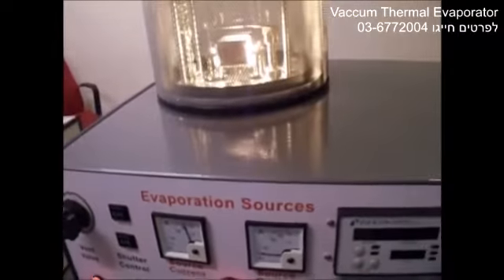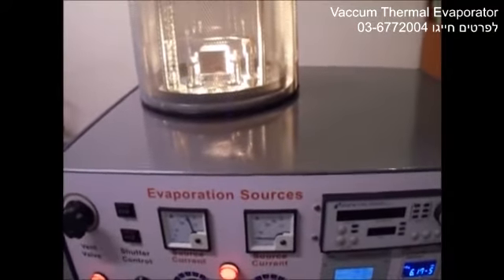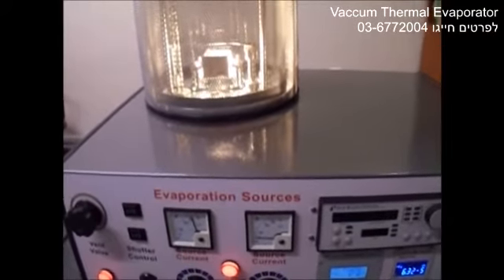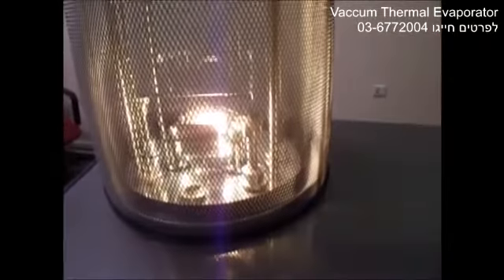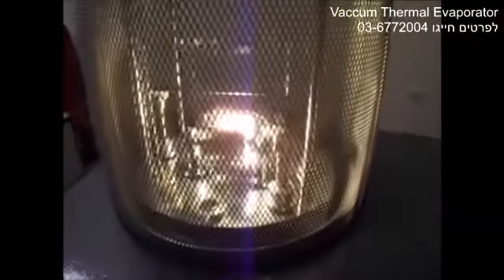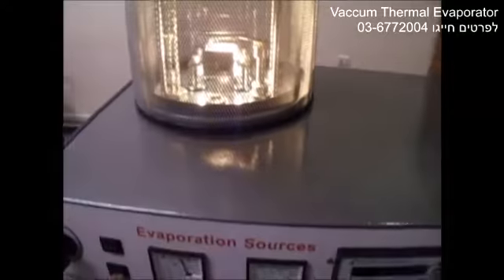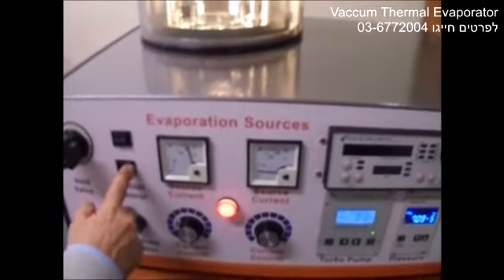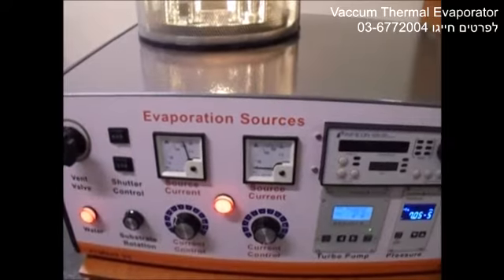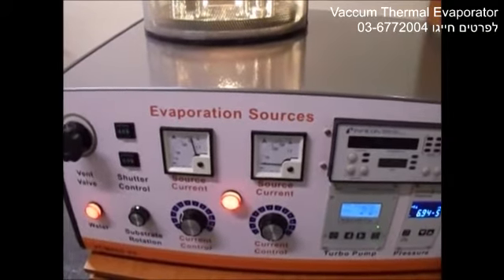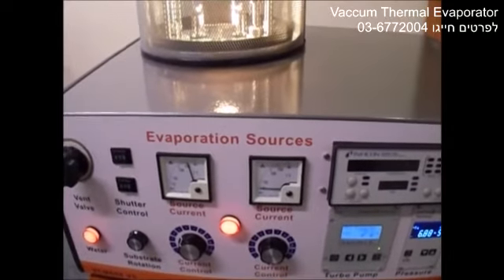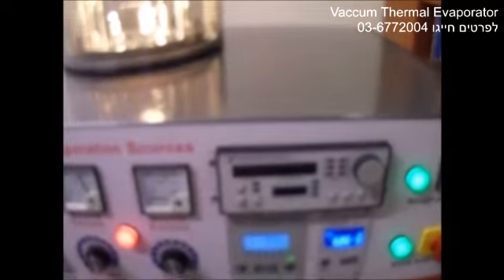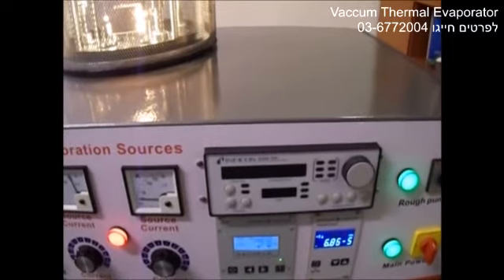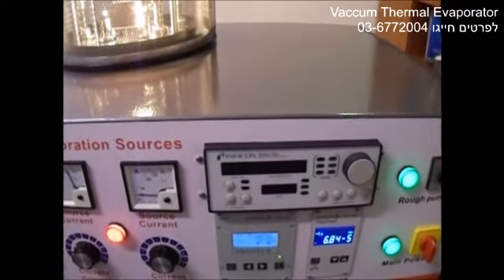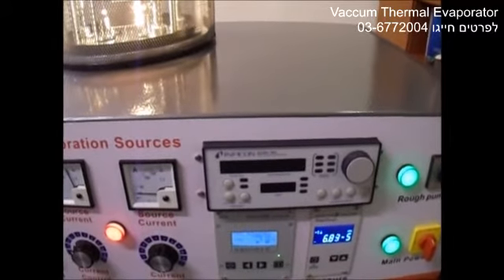The value of the current intensity controls the temperature of the source. As soon as the temperature reaches the desired value, we can start deposition by opening the shutter. Now we have deposition on our sample, and here we will observe on the thickness monitor the thickness of the film that is produced on our sample.